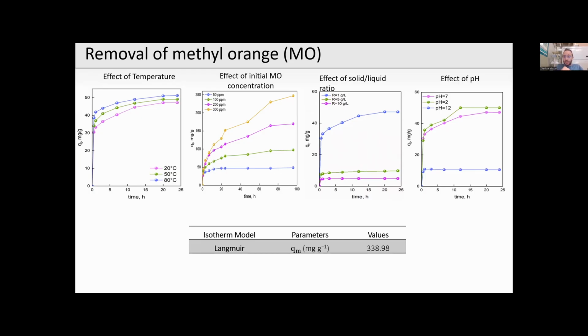While as far as the solid-liquid ratio, as expected, an increase in the adsorbent ratio led to a decrease in adsorption capacity and an increase in the removal efficiency due to the increase in the free and available adsorption sites, which can be used to recover methyl orange ions from water effluents.